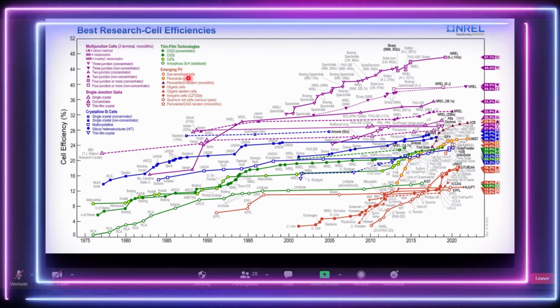And if I look at the so-called emerging cases, or let's look at the multi-junction cases, heterojunctions in purple, you can see they are the highest one. It is about now 40, 45, 46, 47%. And then if you look at the emerging ones with the nanomaterial in orange, where is the orange? Orange is here. You can see still about 25, 26% is coming out. But remember, these numbers are the lab numbers. The robust technology which is out there is still the silicon one, which you can see in blue. It's coming in at about 20-25%, which we have in the market as a silicon-based technology.